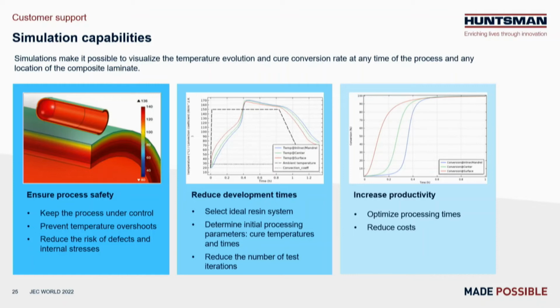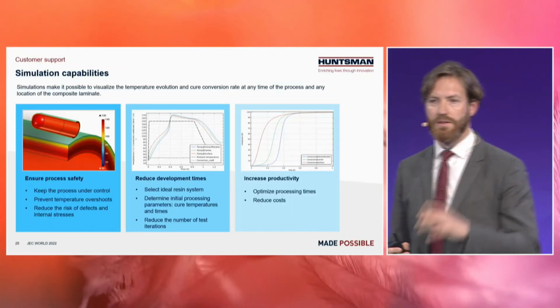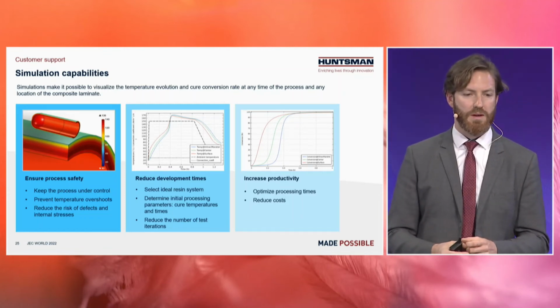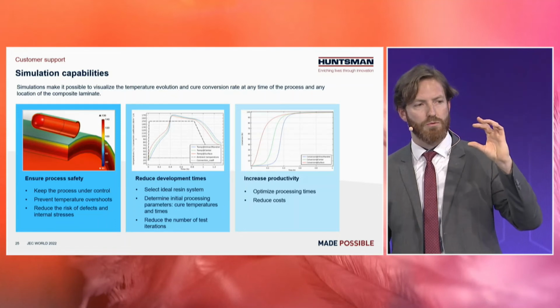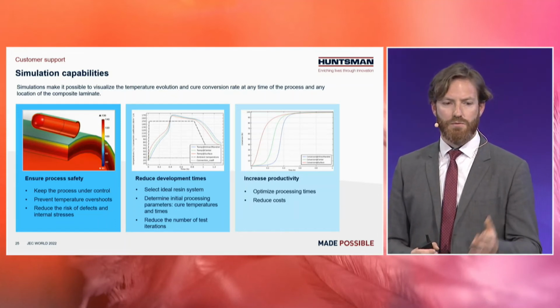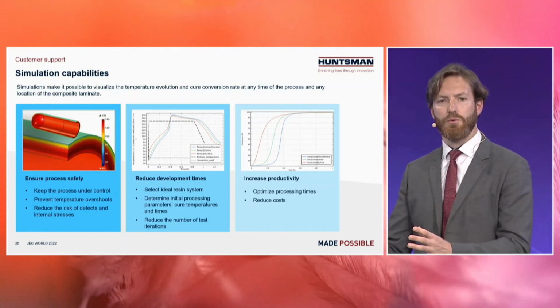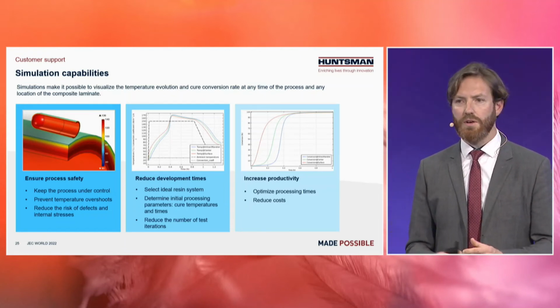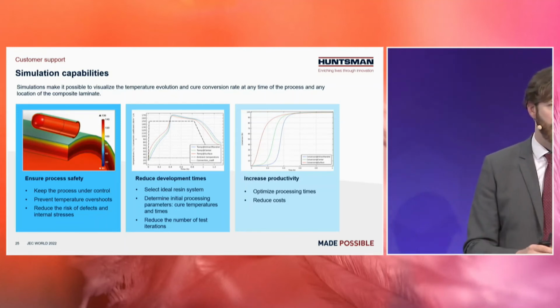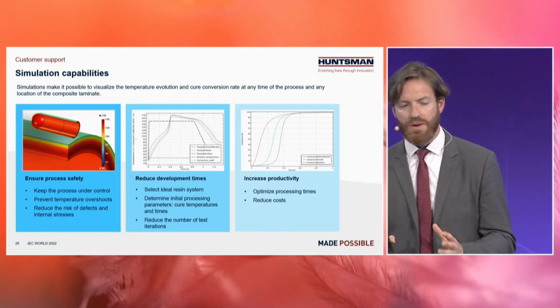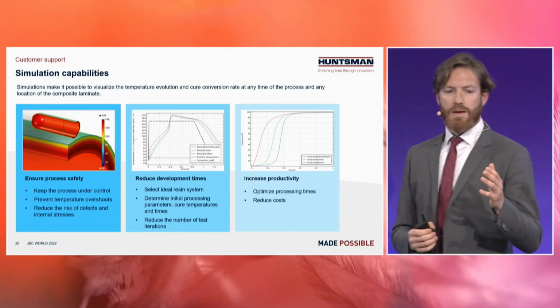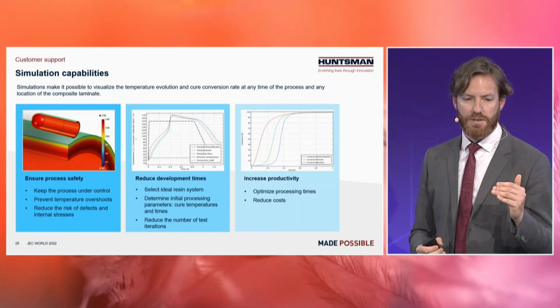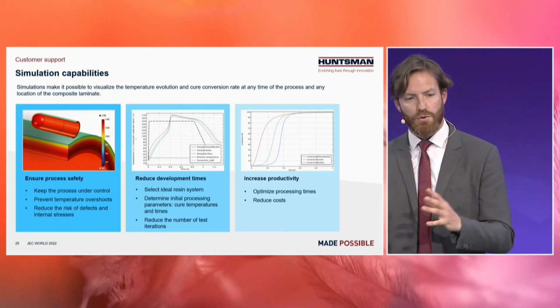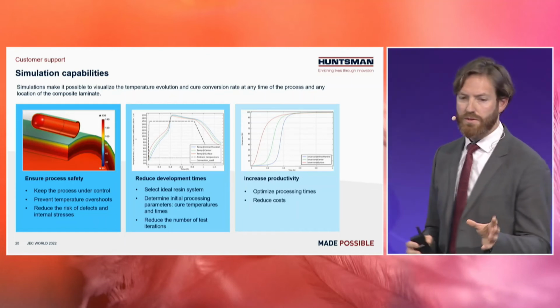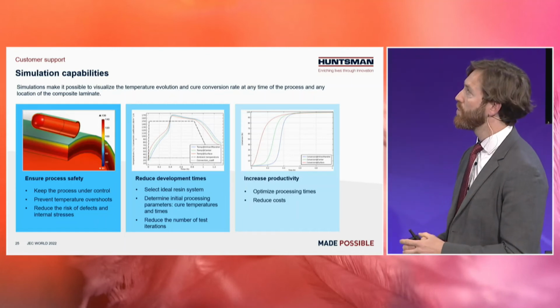So the first element is we can ensure safety, because if, for example, you have very thick materials, and it's the case for pressure vessels, type 4 pressure vessels, 700 bars, sometimes you go up to 40 millimeter thickness. And there, if you put a pressure vessel directly at elevated temperature, you will have a temperature overshoot, which can cause degradation of the resin system, which will lead to porosities, to every kind of defects you don't want to have. So having the simulations helps to prevent those risks. Also, not to have degradation of the liner material, for example. So we can really prevent those risks and keep the process under control.